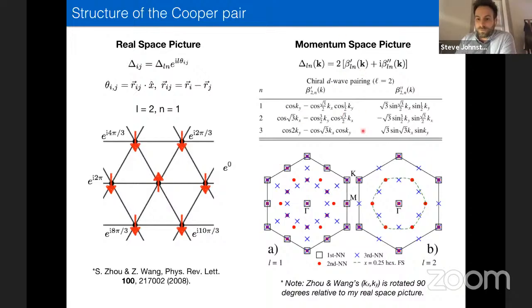There's of course a number of different symmetries that are allowed. So this PRL actually outlines them all. For D-wave superconductivity, you have this sort of nearest neighbor pairing. You have this momentum structure plus this momentum structure. So this is the x squared minus y squared symmetry. This is the dxy symmetry, and of course you get the sum of the two in a d+id superconductor.